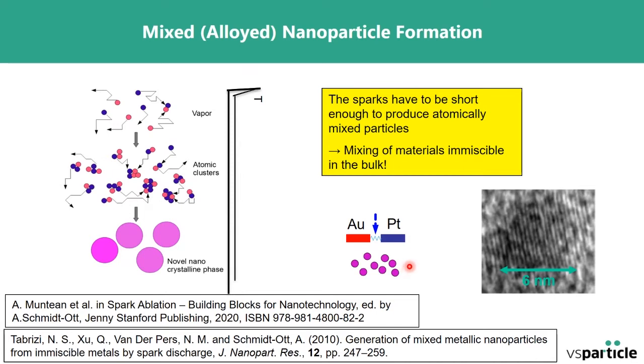Now, in the bulk, that is, in the macroscopic world, gold and platinum do not mix. They do not form an alloy. They are immiscible materials. But it has been known for quite a while that in small particles and also in thin films, the range where metals can be mixed and form alloys is much broader. And so practically always, if the particles are just small enough, you can take any two materials and make mixed particles out of them. Like here with gold and platinum, we see that this 6 nanometer particle is crystalline, and it's an alloy.